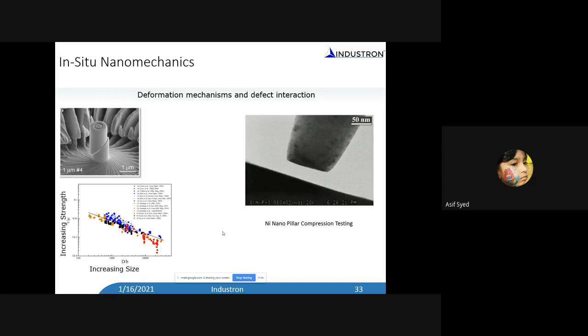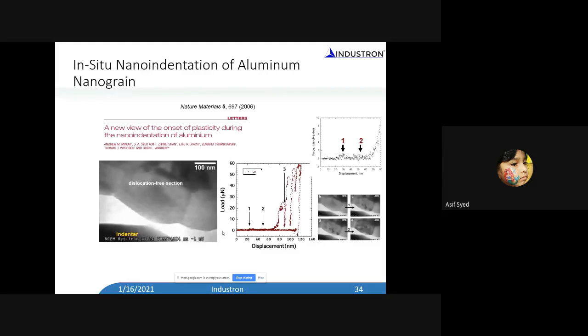This is because of the starvation of dislocations. What is really happening is, for a dislocation to multiply, we know that it has to move a characteristic length. It has to move a distance. Now the pillar is so small, and that characteristic length is much bigger than the pillar size. So before it moves and creates another dislocation, it actually disappears at the surface. That's why all the dislocations are moving to the surface and disappearing, and the material has fewer dislocations, which gives you the strength. This is one of the explanations that we came up with, doing the experiment inside a transmission electron microscope.